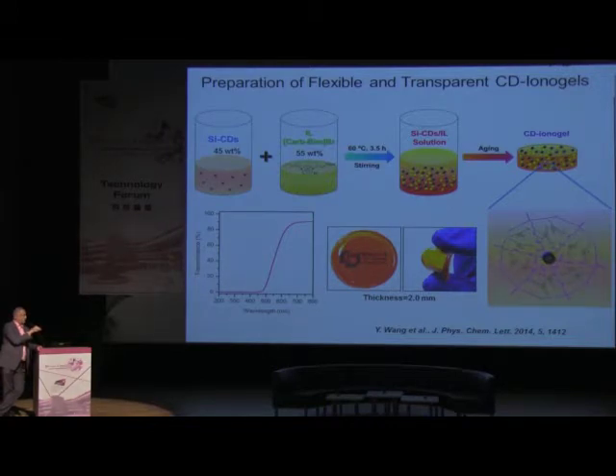So this color which you see here comes from the lower transparency of carbon dots for wavelengths starting from 500 nanometers and longer. While for shorter wavelengths, this material is perfectly transparent for light, which means that we can excite it easily by UV light somewhere here.